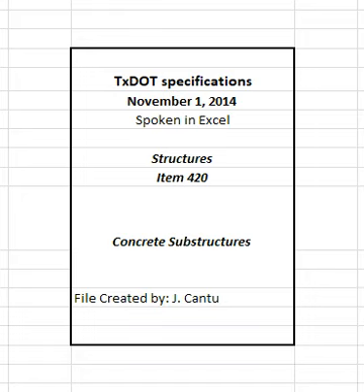Arrange and use chutes, troughs, conveyors, or pipes so the concrete ingredients will not be separated. Terminate such equipment in vertical downspouts when necessary to prevent segregation. Extend open troughs and chutes, if necessary, down inside the forms or through holes left in the forms. Keep all transporting equipment clean and free from hardened concrete coatings. Discharge water used for cleaning clear of the concrete.